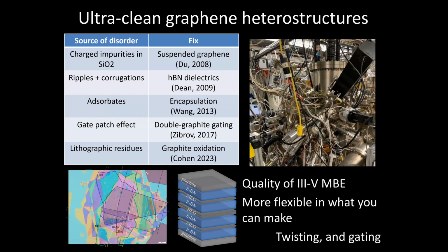But then you also get some more flexibility. So in particular, because you can build in electrostatic gates very easily, take a piece of graphite, a piece of boron nitride and a piece of graphene. The graphite is now one plate of a capacitor, the graphene is another, and you can apply very large voltages because you have this 5 electron volt insulator in between. You have a huge range of number of carriers. You can change the density inside this by a tremendous range. Okay, so you can access all kinds of physics just as a function of density. This is always a property of the experiments.